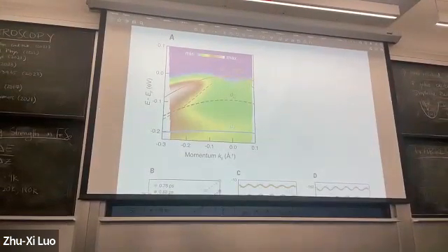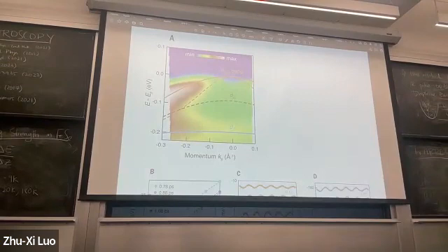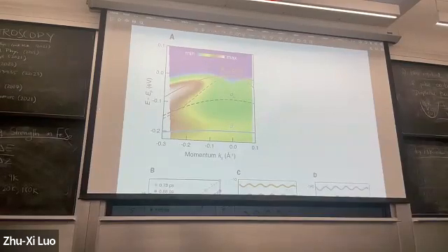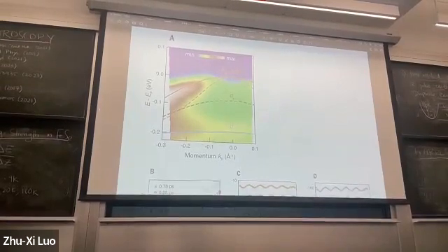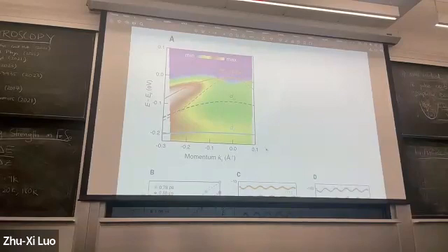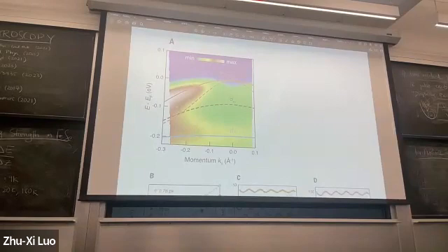Yeah, you're looking skeptical. No, I don't understand. Sorry, I just don't know how to interpret this at first sight. So you can see very broadly the features: the sharp lines are the theory and the background is the actual ARPES data. So you can see very broadly that you get some of the features. Yeah, quite broad. There's various factors behind this, including all of the challenges that I talked about, but also the matrix element between your initial state and your final state, which means that the data can look very different from the theory. This is, I don't think, on a log scale.